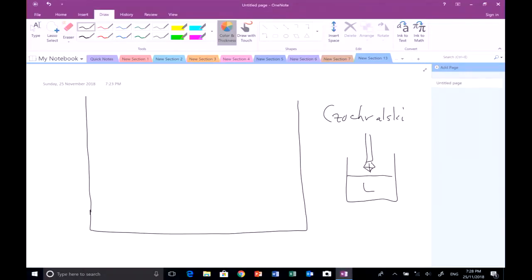And I've seen some pretty big boules, B-O-U-L-E, that were used to make the windows in spacecraft with single crystal sapphire. They were about this diameter. Somebody had a big melt of alumina, and a big crystal to start with, lowered it in and then pulled it up, and that's how they grow these windows and they slice them. This is called Czochralski crystal growth. And to have Czochralski crystal growth, you have to have a molten liquid of the same composition as your single crystal. So what does that tell you is a requirement for Czochralski crystal growth? What do we have to have?